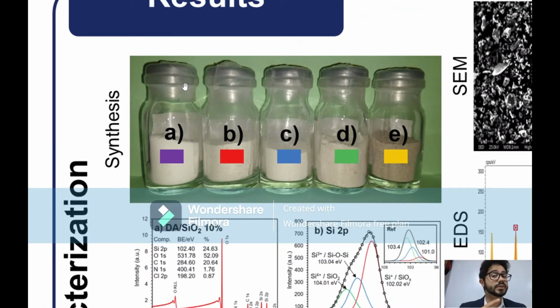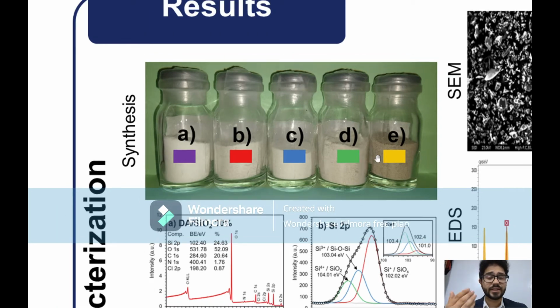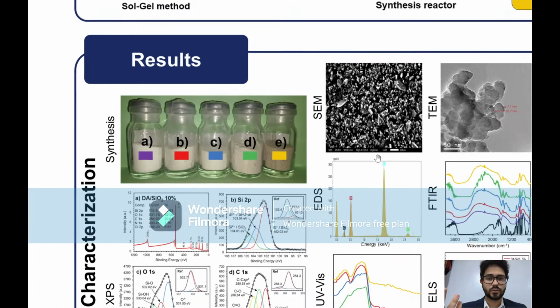dopamine, exhibits a characteristic white color, which is also observed for samples B, C, and D. That is to say, the samples synthesized with dopamine in its basal state. In contrast, sample E, containing oxidized dopamine, exhibits a brownish coloration. This visual assessment serves as a first corroboration of the state of dopamine in the nanoreservoirs. However, this needed to be corroborated by the rest of the techniques.